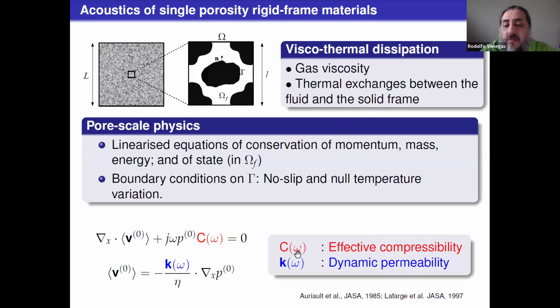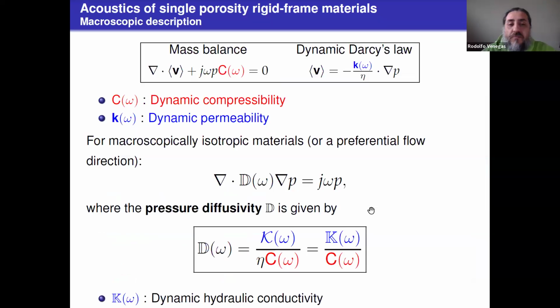In a conventional material, the gas viscosity effects are accounted for by the dynamic permeability K, and the thermal exchanges between the fluid and the solid frame by the effective compressibility. For simplicity, although it is not strictly necessary, if we consider macroscopically isotropic materials, this dynamic permeability tensor becomes a scalar, and we can rewrite these two equations as a diffusion equation where D is the pressure diffusivity. And this calligraphic K is called the hydraulic conductivity, which is basically the permeability divided by the dynamic viscosity of the fluid. This is a very useful equation because it will give us an idea of how the nanoporous material compares with a conventional porous material.